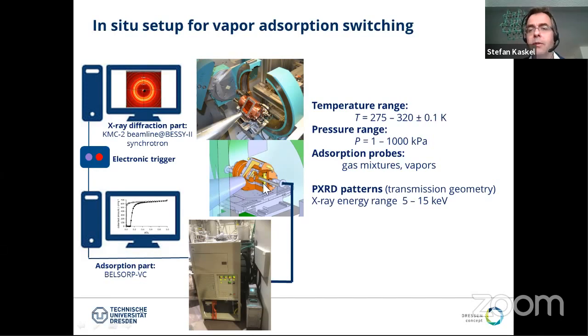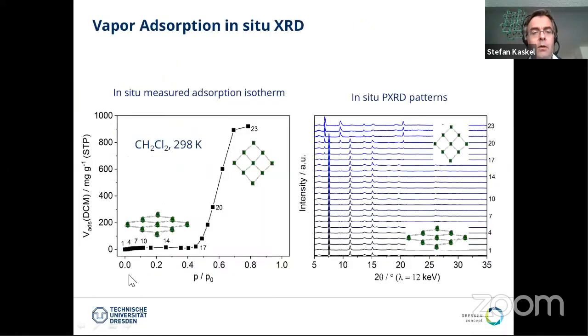And we have developed an in situ chamber to measure vapors at the synchrotron, which can operate at these temperatures and pressures indicated here. I just show you basically along the adsorption branch. Here we see the gate opening. This is for the nickel system. For dichloromethane, this is the isotherm that we measured, and you see a clear gate opening at a pressure of 0.5 in P over P0.